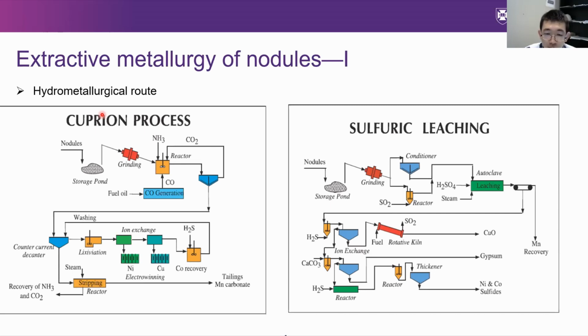One is the hydrometallurgical route to treat the nodules. From the left figure, in the Cuprion process, the nodules are ground to fine powder and then reduced by carbon monoxide gas in a stirring reactor. This reactor is in the presence of ammonia, and then copper, nickel, and cobalt are made soluble in this decanter, and nickel and copper are extracted by liquid ion exchange and combined with electrowinning to produce pure metals. And the cobalt is removed by sulfide precipitation.